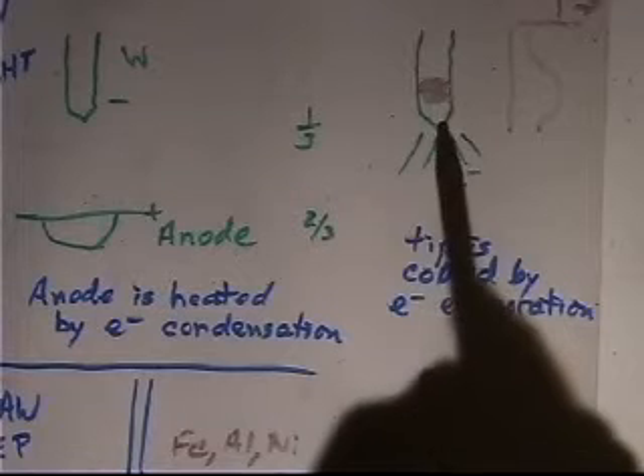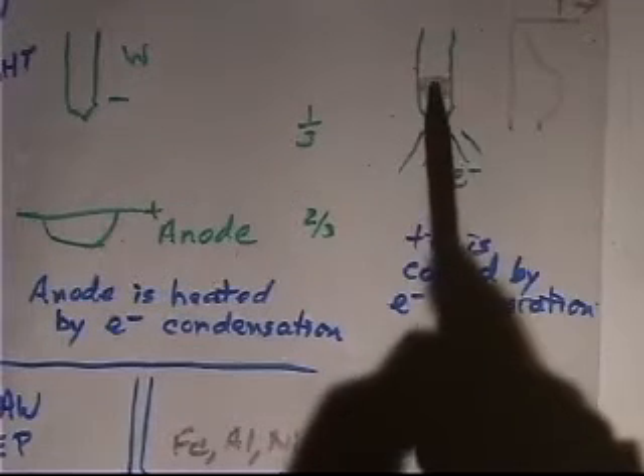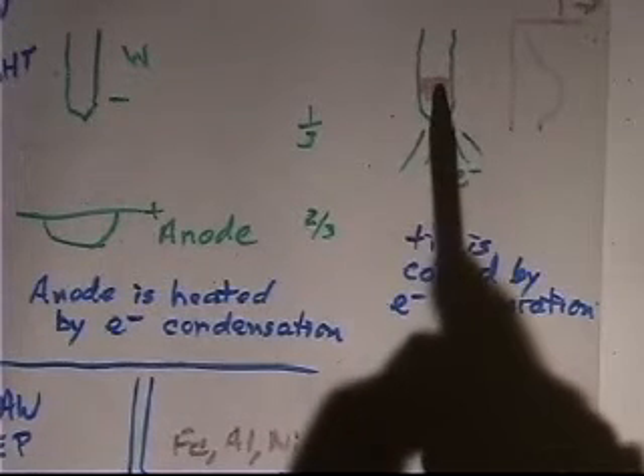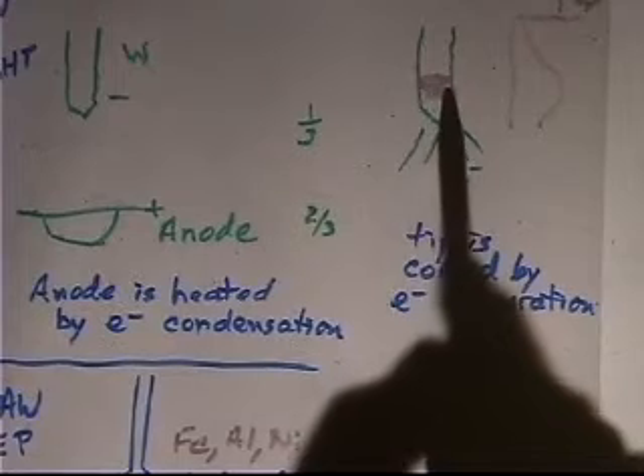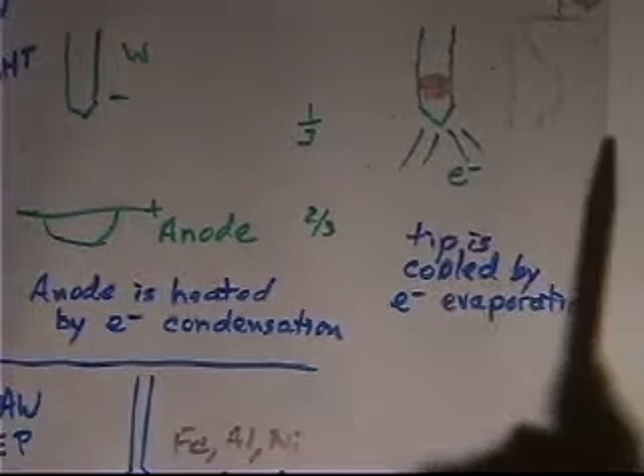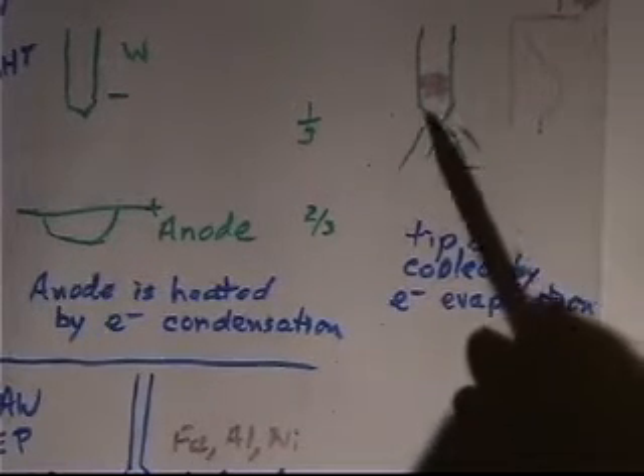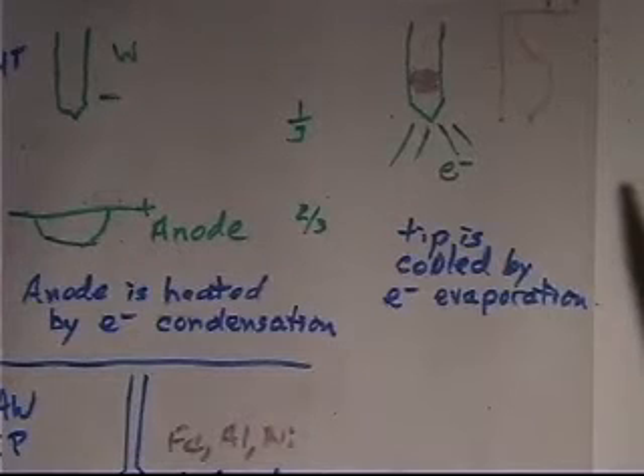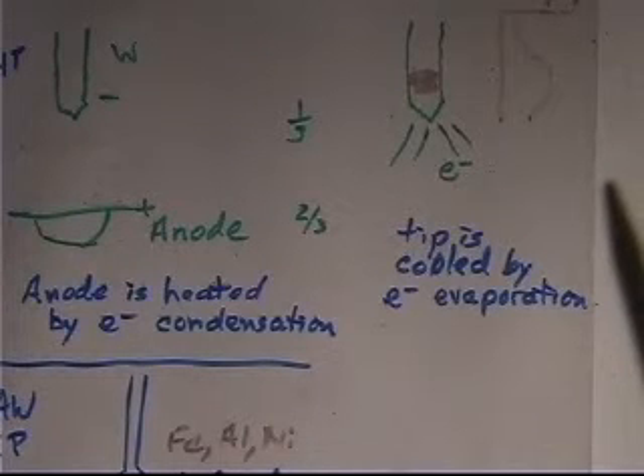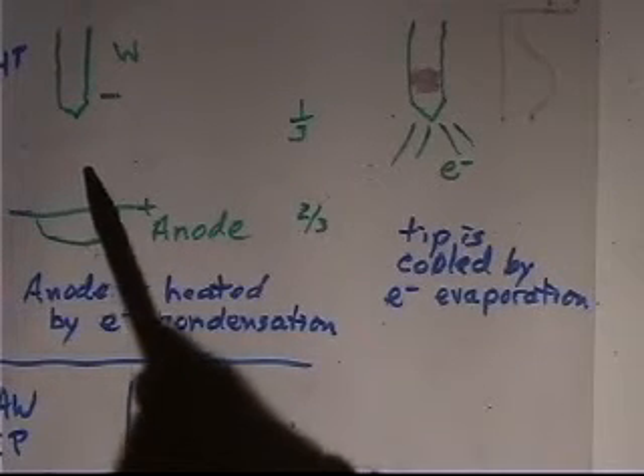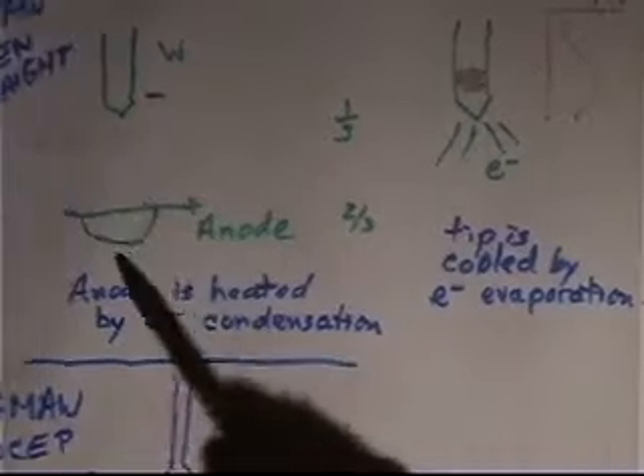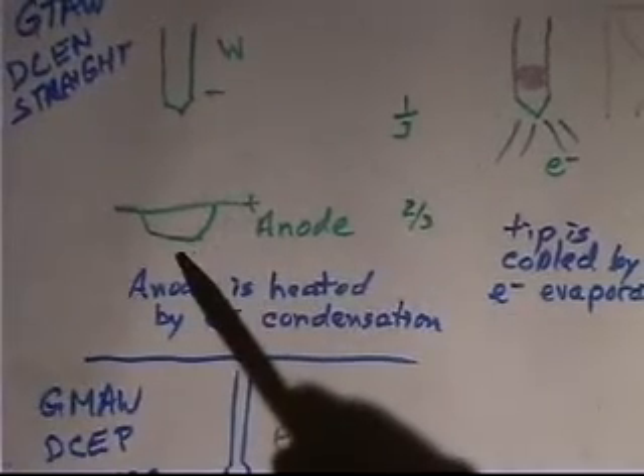He shielded off the arc, and he measured the temperature of the electrode, and the gas tungsten arc electrode was hotter a couple of millimeters from the tip, because it actually is being cooled by the surface, by the electrons coming out of the surface. By the same token, when the electrons go into the anode, they're heating the anode. They carry that work function voltage in there.